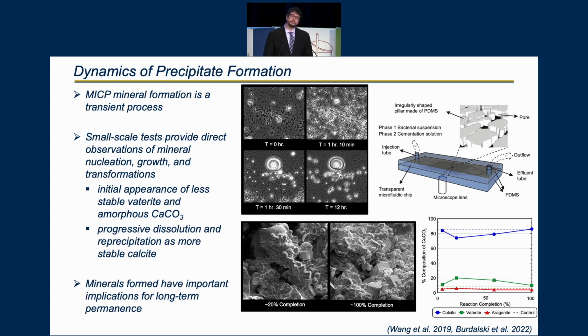We see the appearance in particular of less stable vaterite and amorphous calcium carbonate, with these crystals or minerals progressively dissolving to form more stable calcite. This can be verified visually through the images which we're seeing here, but it can also be quantitatively confirmed using X-ray diffraction, which can assess mineral presence. Of course, the minerals that are formed during these systems are going to be quite important when we start to think about what is the longevity of this material and how long might it exist at a particular project site.